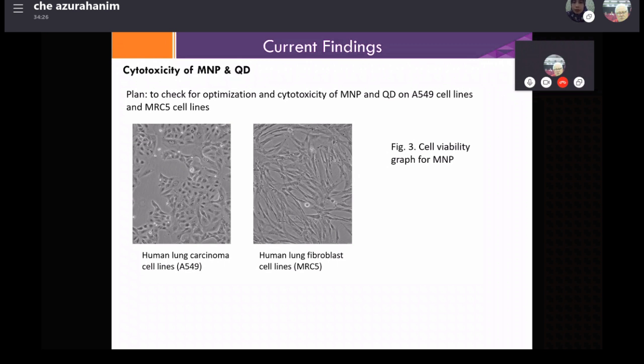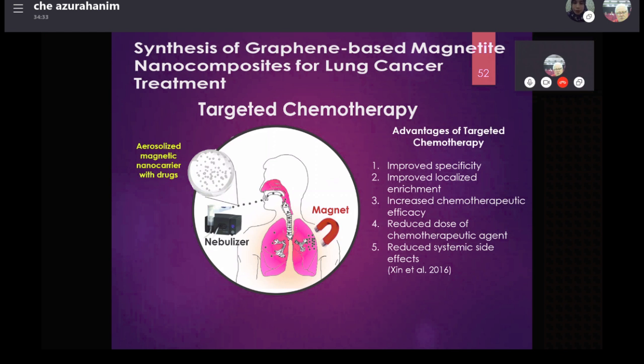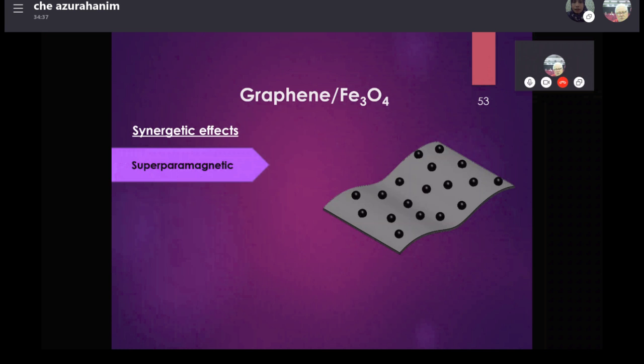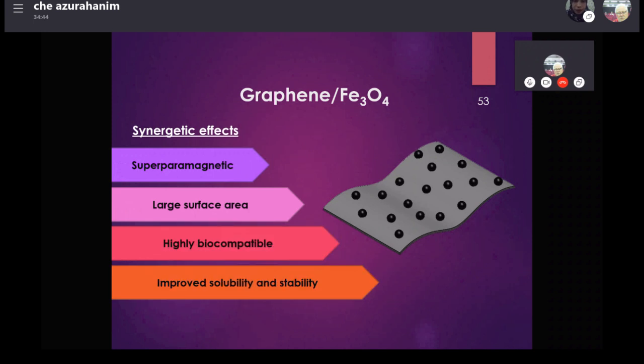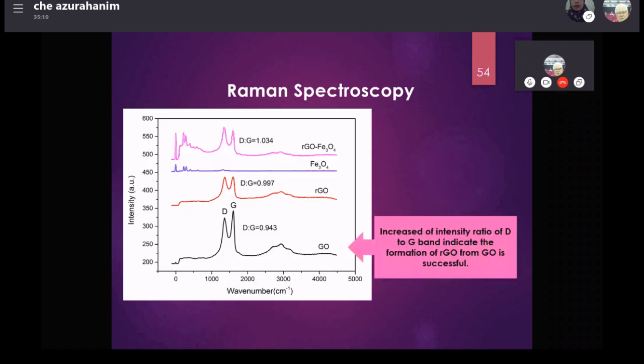Here is another study by another student, where we synthesize a graphene-based magnetite nanocomposite for lung cancer treatment. More or less similar to the previous study, but now she's using graphene. Because of graphene, we have a synergistic effect. That means superparamagnetism from the iron oxide, large surface area from graphene, and the mixture is highly biocompatible and improved in terms of solubility and stability. Here is the Raman spectroscopy, showing that the increase in the intensity ratio of the D to G band indicates the formation of RGO from GO is successful.